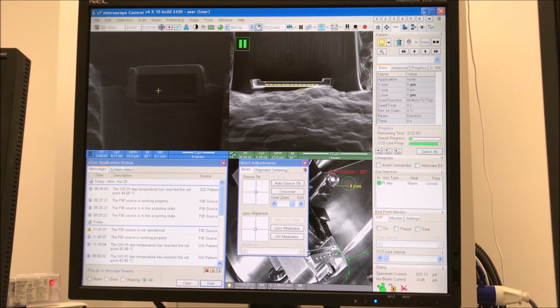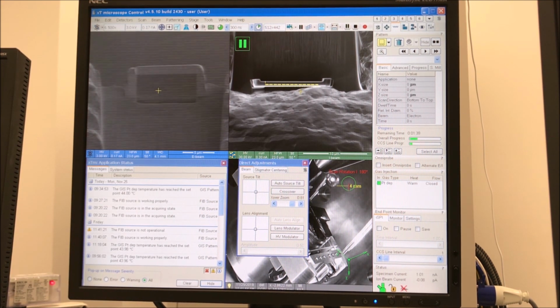So this produces a series now of staggered cuts into the lamella, if you will, which empirically helps to keep it more mechanically stable than if I keep that X dimension the same, and it also saves time. It will result in a little bit less usable area than you might otherwise get, but in TEM your sampling is terrible anyway, so that's really not something that should be a huge consideration.